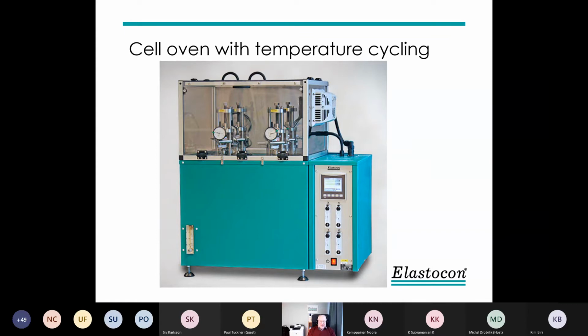The normal ovens have a steady temperature. This is an oven where we have cycling temperature, and it's equipped with cooling water. You see the flow meter in the front. Here we can cycle between an elevated temperature up to 300 Celsius and down to room temperature 23 Celsius. It means we can do method B, where the measurements should be done at room temperature, and the aging at higher temperature, we can do that automatically, and we don't need to take the test jigs in and out of an oven and do manual measurement.